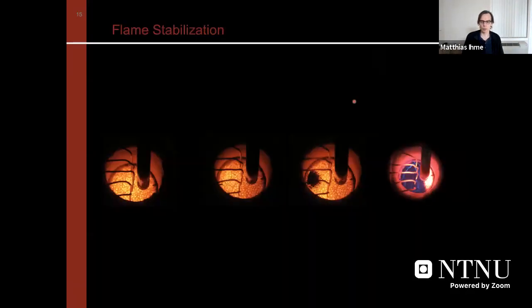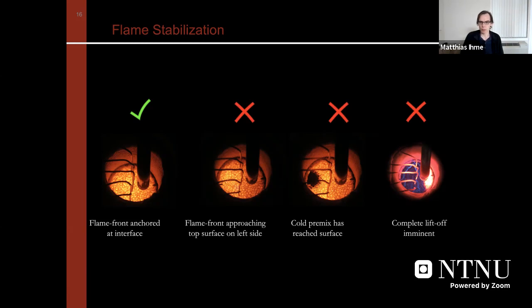In terms of describing the performance of these porous media burners, we're primarily using visual inspection to determine the flame stabilization. What you're seeing here in the first system, looking from the top, is a very homogeneous flame temperature across the heating system. That means that the flame is well anchored. In this middle region, you're seeing that the flame slowly starts to break through. We're seeing some dimming, eventually the loss of the flame, and this final stage means that the flame detaches, it's pushed to the top of the burner. With this, we are not stabilizing the flame anymore, and it's lifted off. So this is essentially the instability limit.